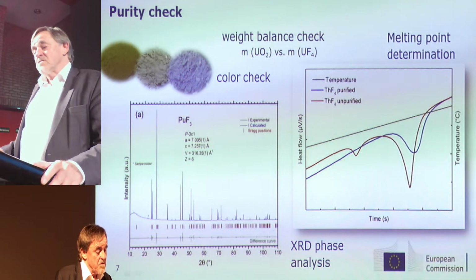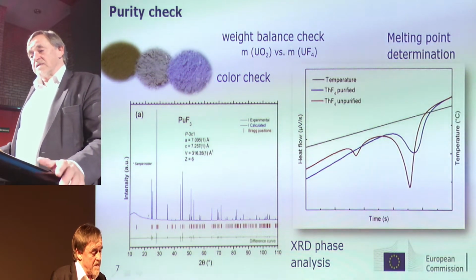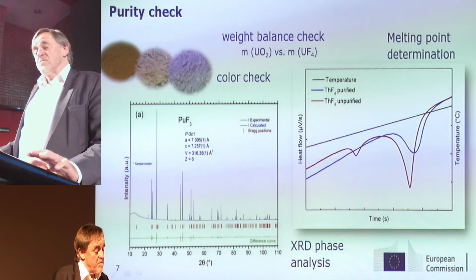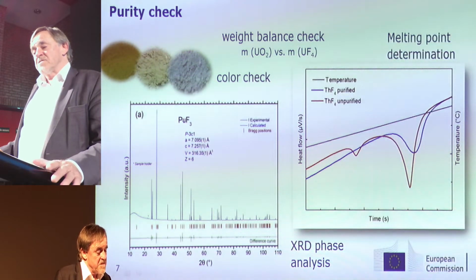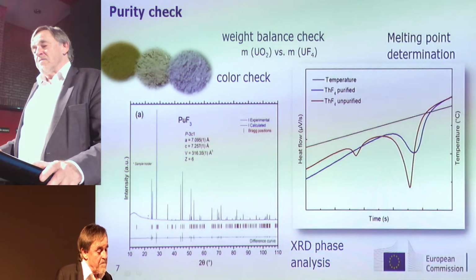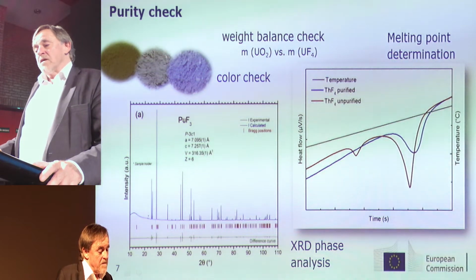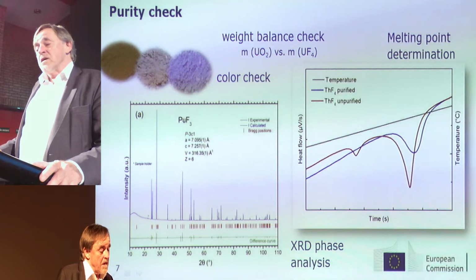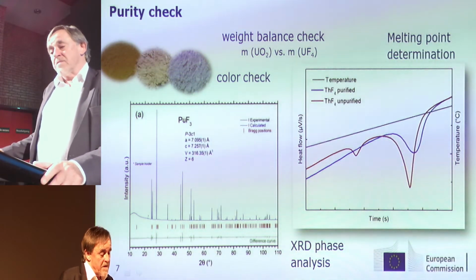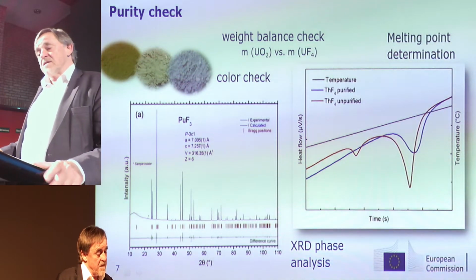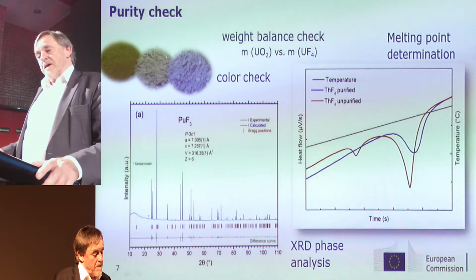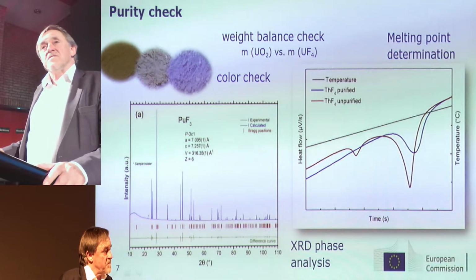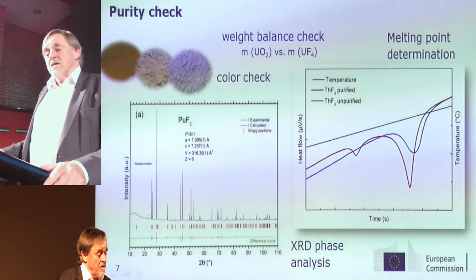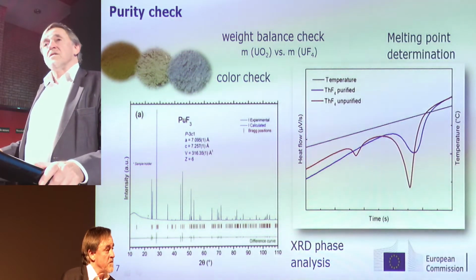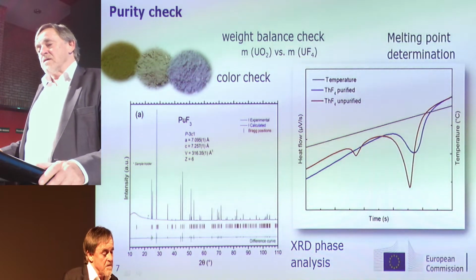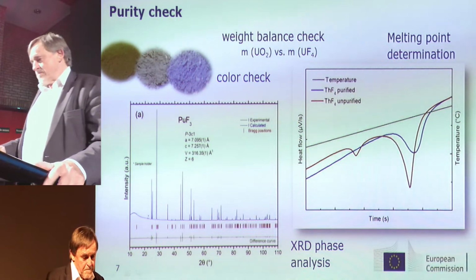And last but not least, also an XRD phase analysis, where we use three systems: the experimental work, the calculation work, and the data which are found in the database, and try to make a comparison and an identification of the different peaks, also a good indicator for the purity of the product that is obtained, in this case the plutonium fluoride.